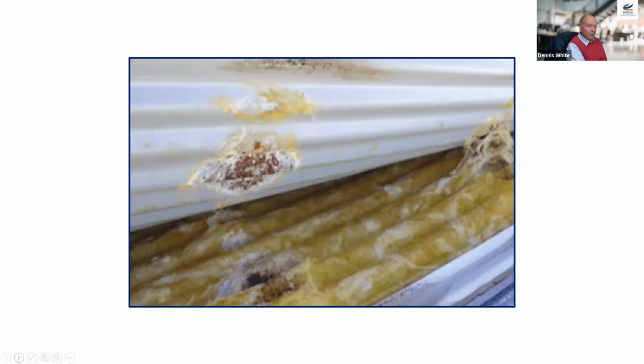And the best way to avoid any problems with wet storage, staining, corrosion, is to store the materials on dry, untreated dunnage to start with. If dunnage is wet, some of the preservatives, if it's got preservatives in it, will attack your coating, and they must be a minimum of 200 millimeters above the surface on which they are stored. That surface itself must be firm, quick drying if it's like a roadway or something like that. Preferably it should be an impervious underlying surface that is permanent, or is dry most of the time.